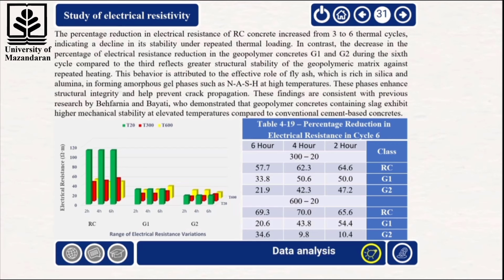This behavior is attributed to the beneficial role of fly ash, Fa, with its high silica and alumina content, which promotes the formation of stable amorphous gels, such as N-A-S-H, at elevated temperatures. These gels not only strengthen the matrix, but also help prevent crack propagation.